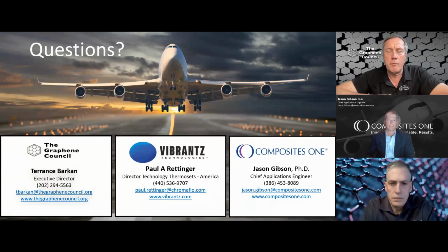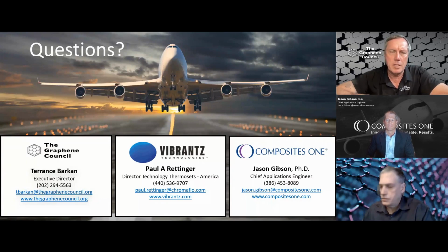So, for example, everybody may be familiar with the fact that Ford Motor Company used a graphene-enhanced polyurethane material in the engine compartment for the F-150 and for the Mustang. And they did that for thermal heat transfer properties. But they also got a reduction or a dampening effect in vibration. It also reduced the flammability, and we've seen this with other applications of polyurethane with graphene added to it for strength and wear resistance, that it reduced the flammability of the material.